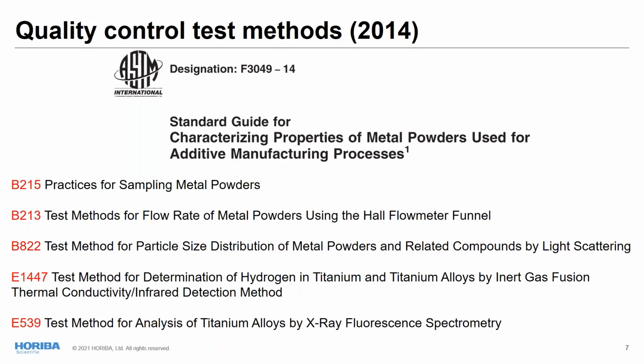And here I have a list. I would say, as with any analytical tool you're going to use, the first step is to get the ASTM standard to know exactly how to sample your material for whatever analysis you're going to perform. This material can be very heterogeneous and is very hard to sample. It is important to have good representativeness of your sample, so you can trust your results, because this can vary a lot just due to the sampling system you use.